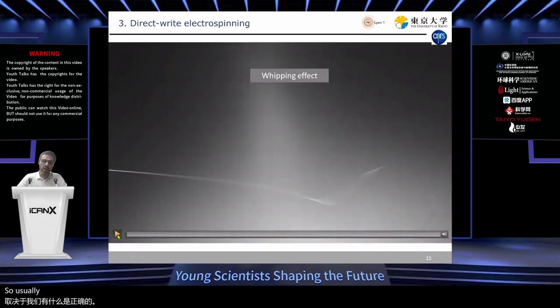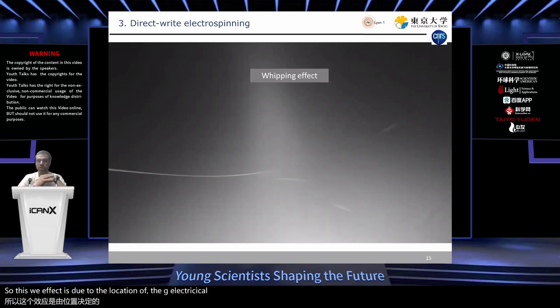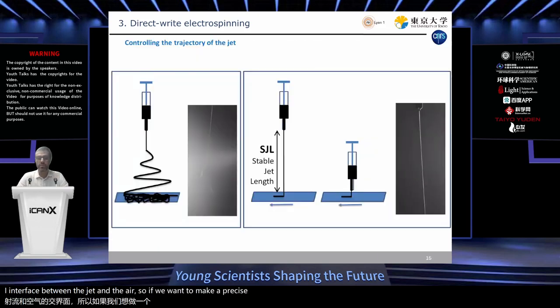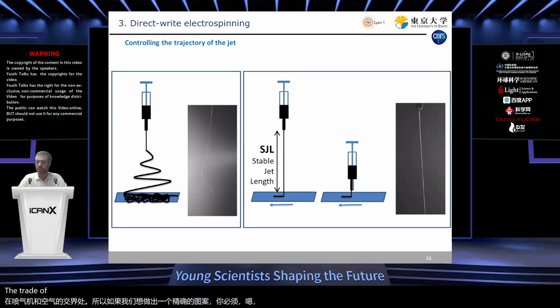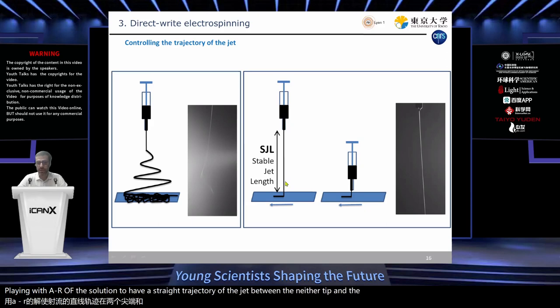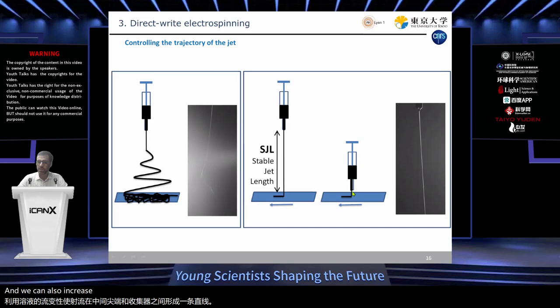So usually we have a whipping effect. Here you have on the left-hand side the nozzle, and on the right-hand side the collector. This whipping effect is due to the location of the electrical charges at the interface between the jet and the air. So if we want to make a precise pattern, we have to get rid of this whipping effect. We can do it by playing with the rheology of the solution to have a straight trajectory of the jet between the needle tip and the collector. And we can also increase the accuracy of the deposition by decreasing the working distance between the needle tip and the collector.